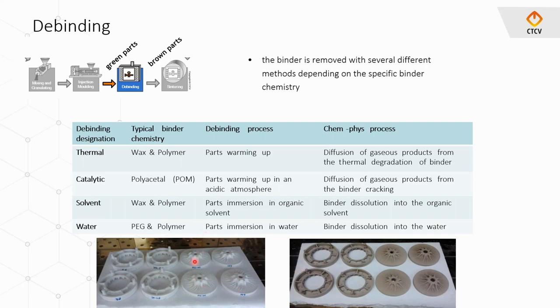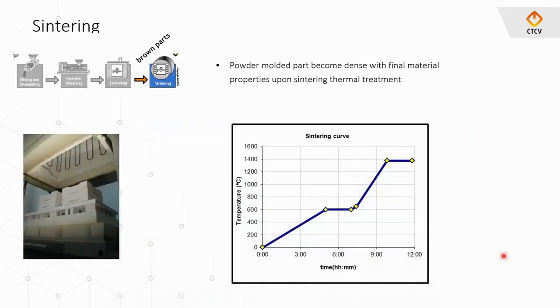Here we can see the green parts in the left picture and the brown parts after the debinding in thermal way. After debinding, we proceed to the last step, sintering, which is very common in the ceramic world, as everyone knows. And typically we have a thermal profile starting with one phase of binder burnout. So in the debinding phase, we do not remove the whole binder. We keep some 5 to 20% of the binder to go through the sintering furnace in order to retain the shape of the part.